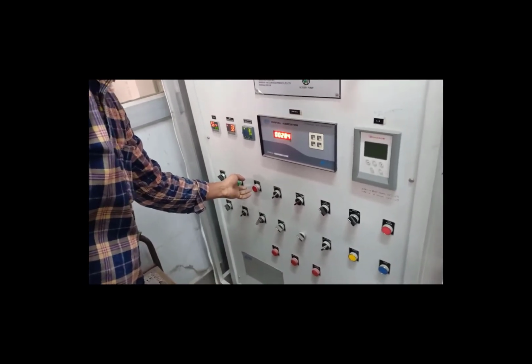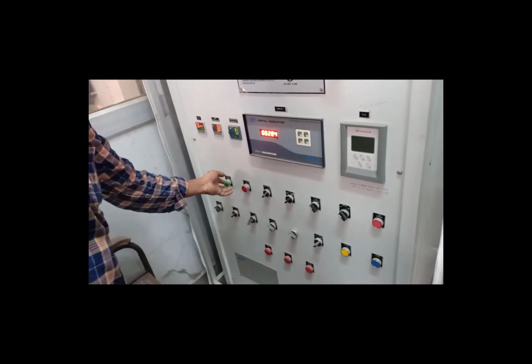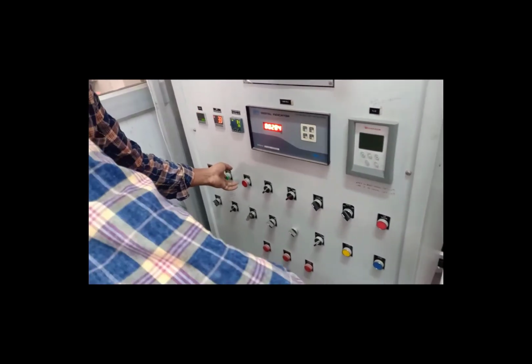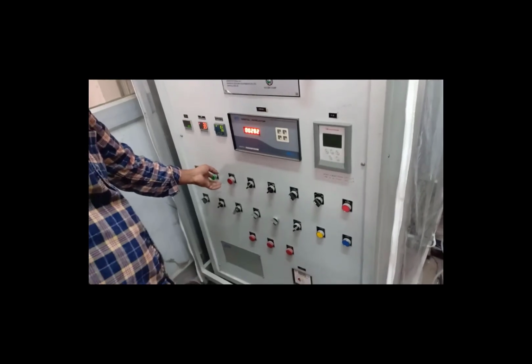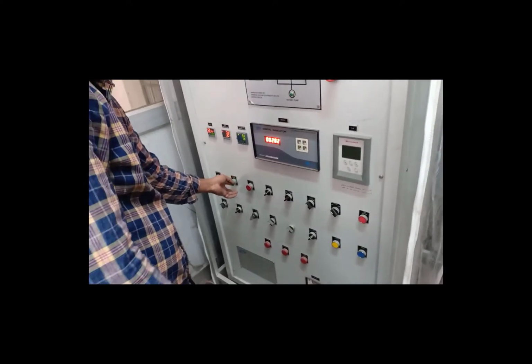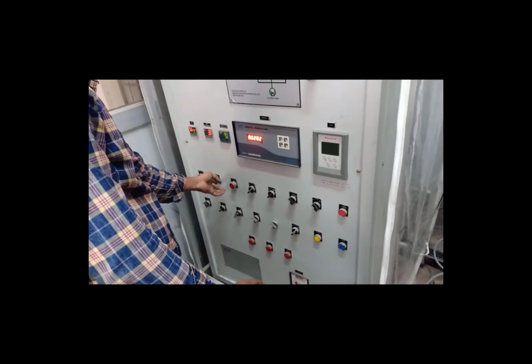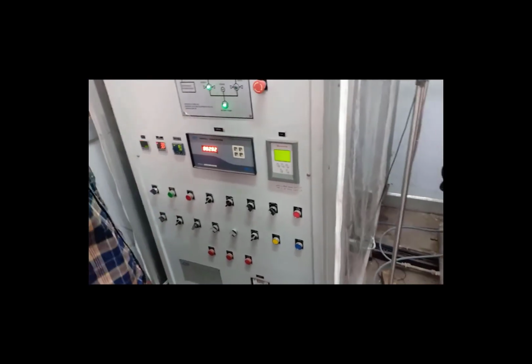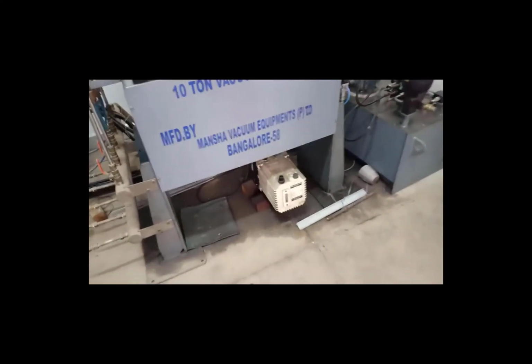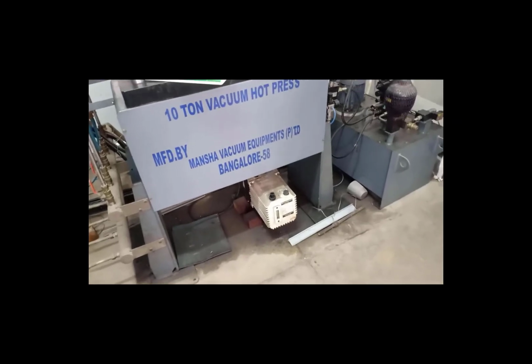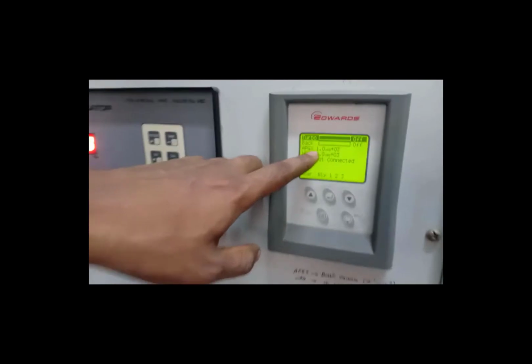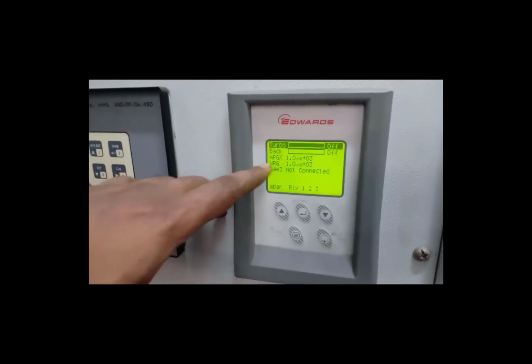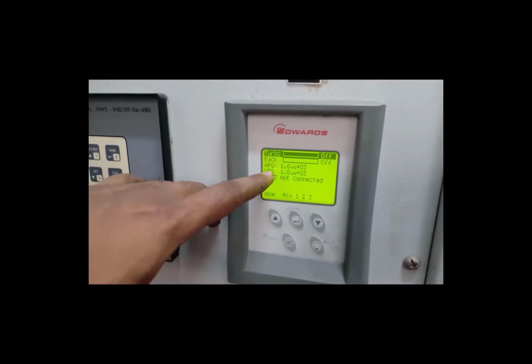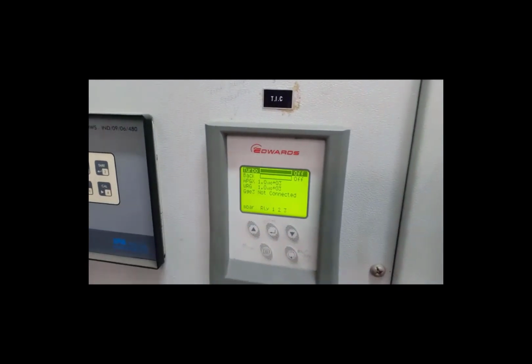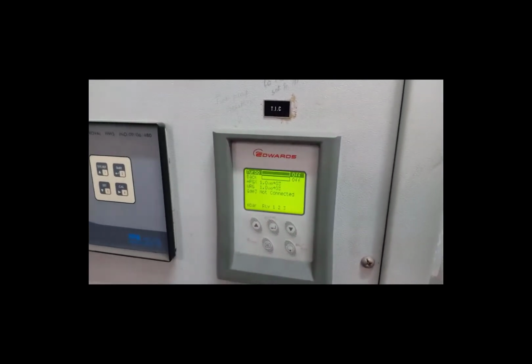So we need to create a vacuum. For that purpose, different pumps are used here. One is the rotary pump, another is the diffusion pump. The diffusion pump is for high vacuum. This is only for a basic vacuum requirement. With the rotary pump running, you can see that there are two gauges. One is the APGX, Active Pirani gauge, and another is the WRG, wide range gauge. This should be in the 10⁻² or 10⁻¹ range.